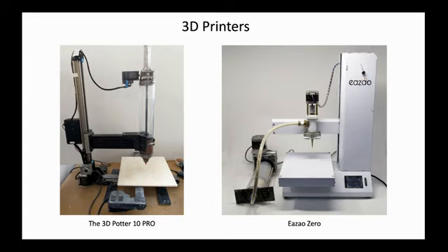The Eazao has a plunger that pushes clay through a smaller tube, and then a second motor that controls an auger, which is a screw that pushes clay out of the nozzle. The consistency of the clay used for this machine needed to be much softer, closer to a thick frosting consistency. Both of these printers are commercially readily available.